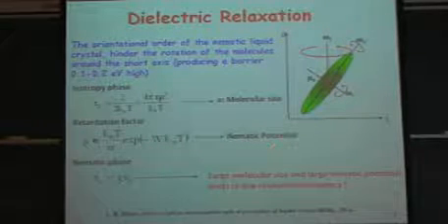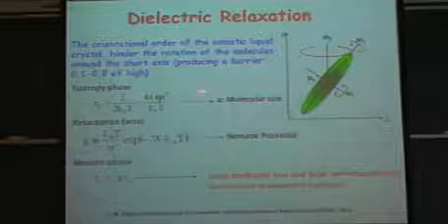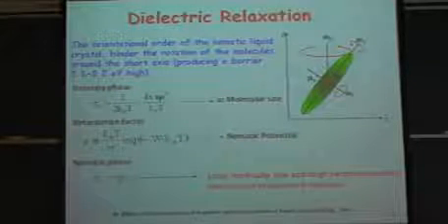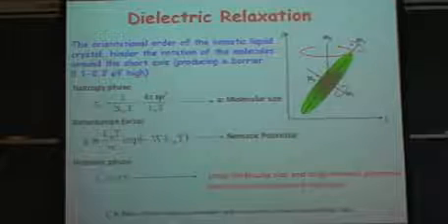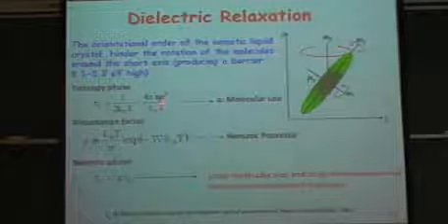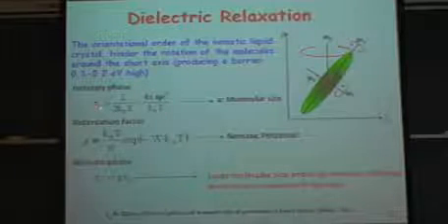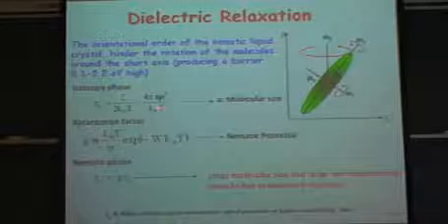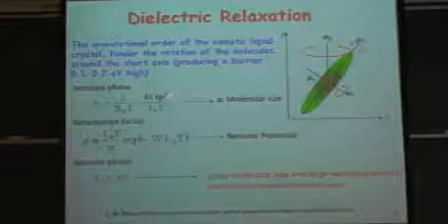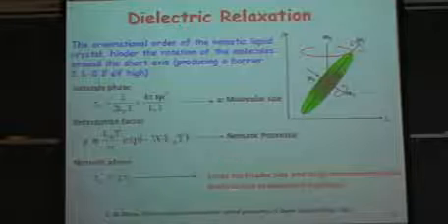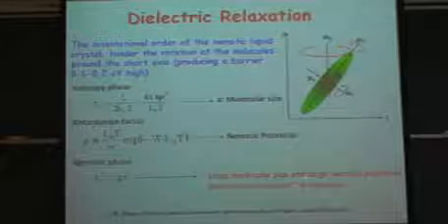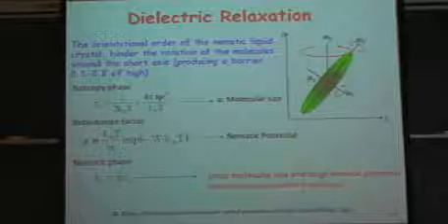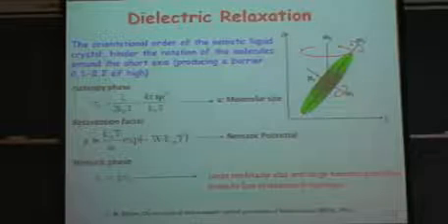And also in this book, they set up a model. You can look at the liquid crystal as a sphere suspended in an isotropic medium with viscosity eta. And this shows the relaxation time of the liquid crystal molecule is proportional to, related to, its size. So in conclusion, we think the large molecular size and large nematic potential lead to low relaxation frequency.